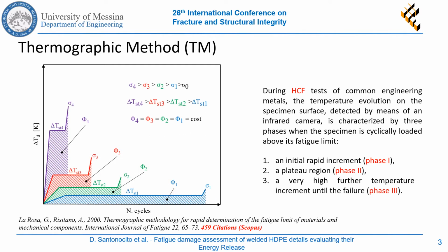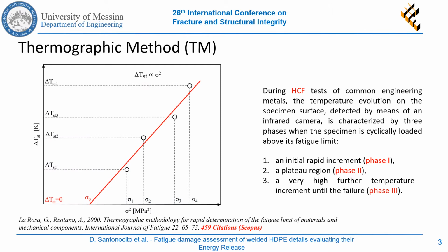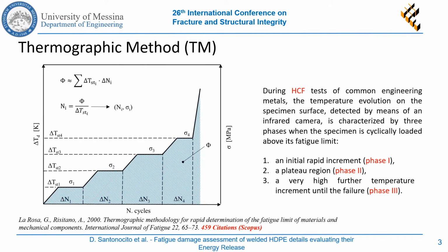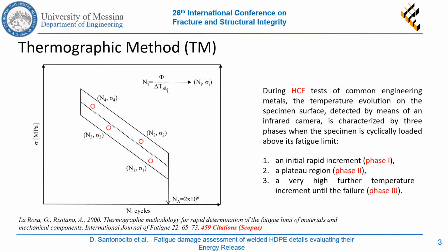Generally, the higher the applied stress, the higher the stabilization temperature, but on the other hand, the subtended area of the temperature versus number of cycles curve could be assumed constant and related to an energy parameter phi. If we report the stabilization temperature versus the applied stress, the fatigue limit of the material could be defined as the intersection with the stress axis. In addition, if we stress in a stepped way the material and we evaluate the energy parameter and the different stabilization temperatures, it is possible to obtain the number of cycles at which the material will be broken if we cyclically test with that stress, hence obtaining the SN curve.